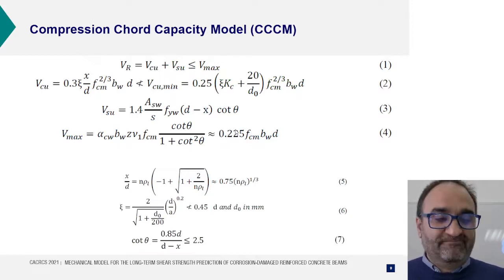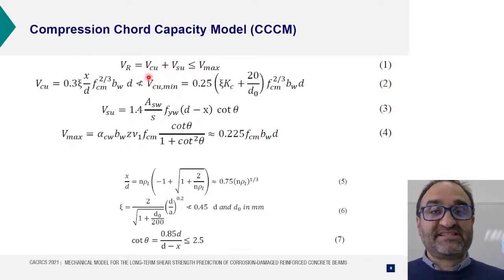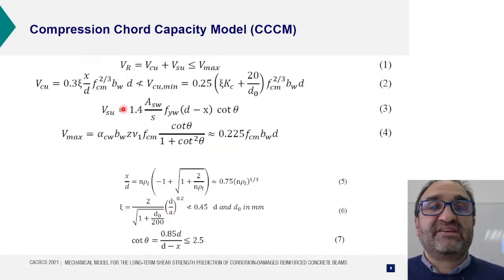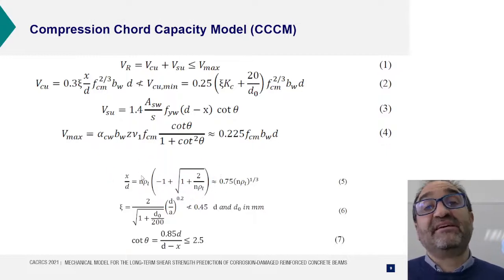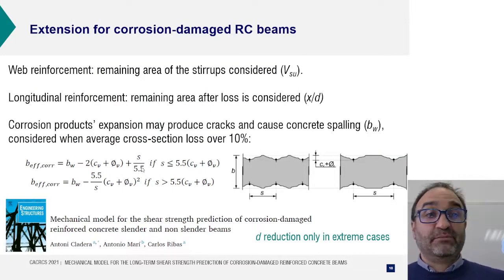I'm not going to fully enter into the model, the Compression Chord Capacity Model, but at the end you have a concrete contribution plus a steel contribution. The steel contribution is from a classic truss model, and the concrete contribution considers a size effect. Here, this term comes from fracture mechanics and was developed by Professor Bažant, and the relative neutral axis depth is, let's say, the key of the model.